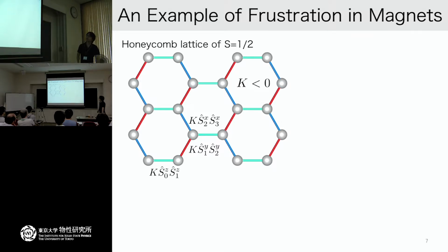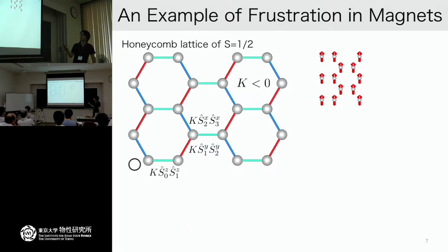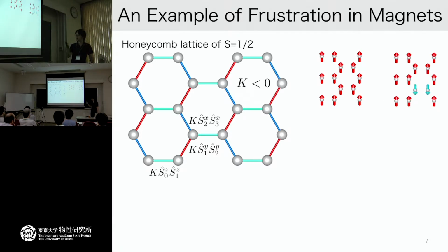Okay. Then let me examine how this system shows frustration. First, we assume that the Kitaev coupling is dominant, and we only take into account this Kitaev coupling here. Usually it becomes negative in the ruthenium or iridium compounds. If you try to find the classical ground state of this lattice Hamiltonian, one possible ground state is something like this, where all spins point along the z direction. This gives one candidate for the classical ground state. However, remember that only the z component of the spin interacts through this horizontal bond, so if you flip one pair of spins, you can keep the energy the same as this configuration.